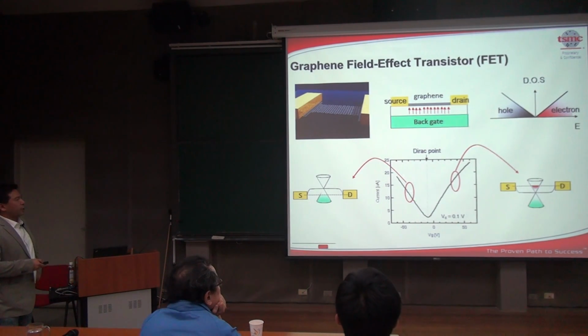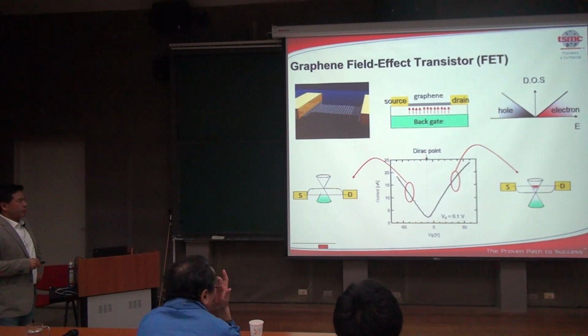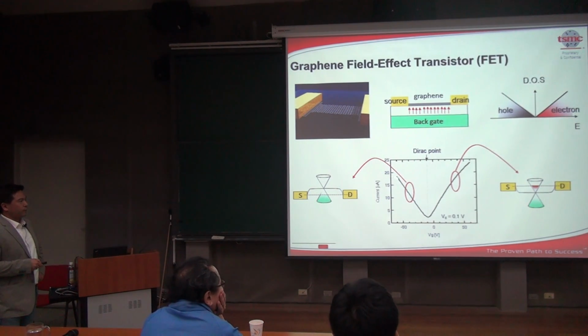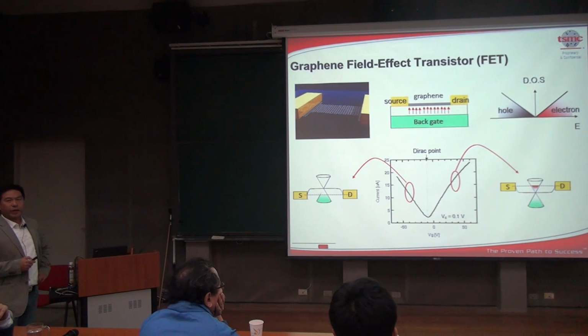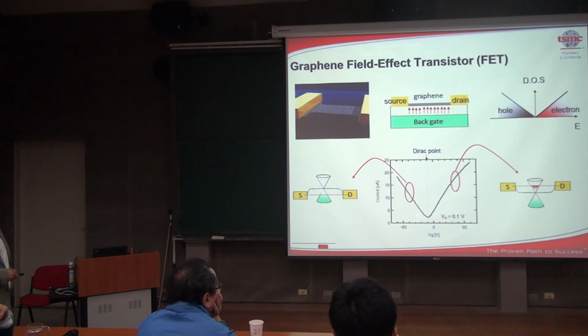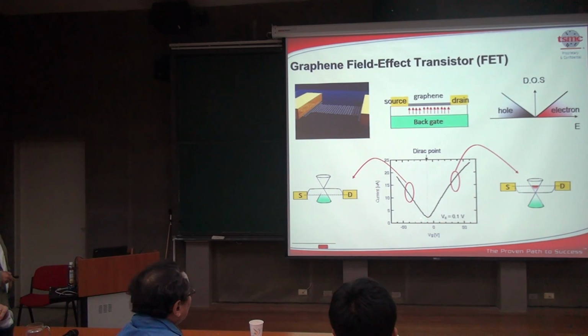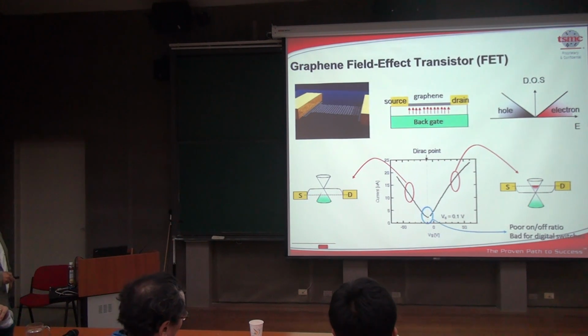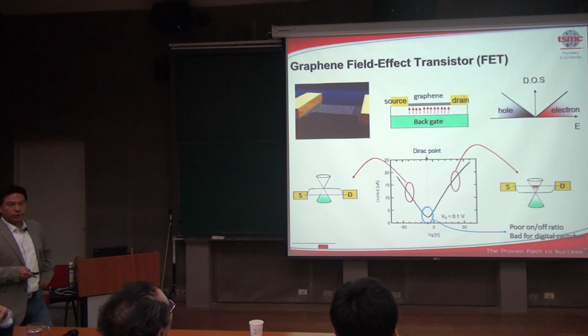So this is a current as a function of gate in a graphene device that shows this, we call it ambipolar device characteristics, that the current can be modulated by the gate from high current to low current and back to high current again. You have this shape because you can have transport due to holes or electrons depending on your Fermi energy. And as I will mention again here, this is the off state, so-called off state. It still has a finite current, actually quite substantial current. So we call it very poor on-off ratio, very, very bad for digital switches.